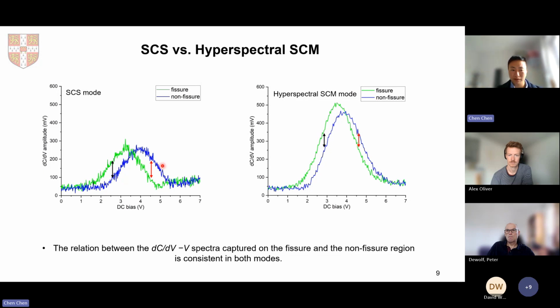In both cases, you can see that at this bias, the fissure shows a bigger dC/dV amplitude value than the non-fissure region, and the situation is just opposite when the DC bias increases. So we expect we may see contrast between the fissure region and the non-fissure region if we scan at these two DC bias values.